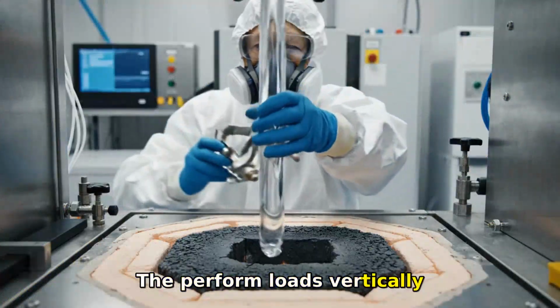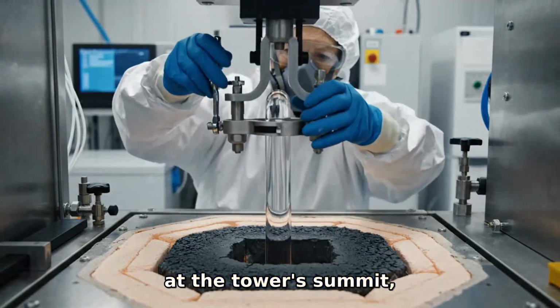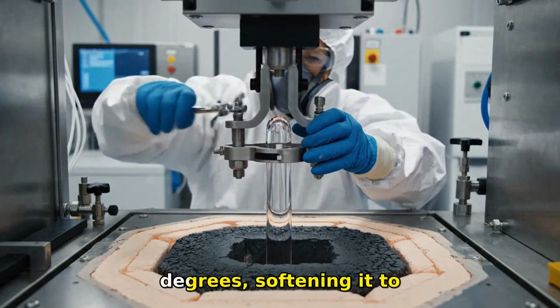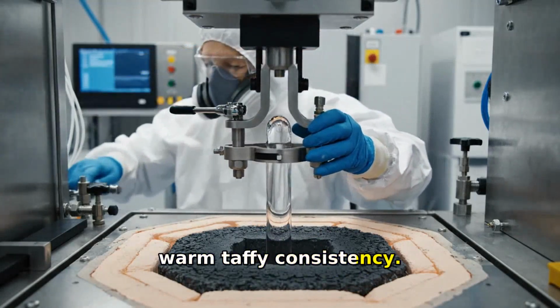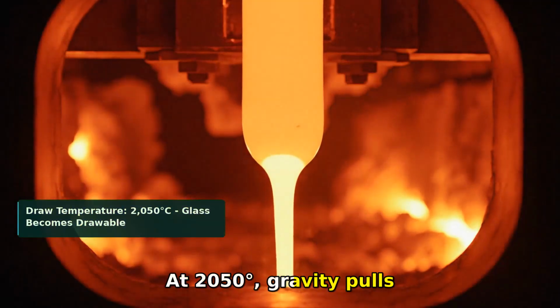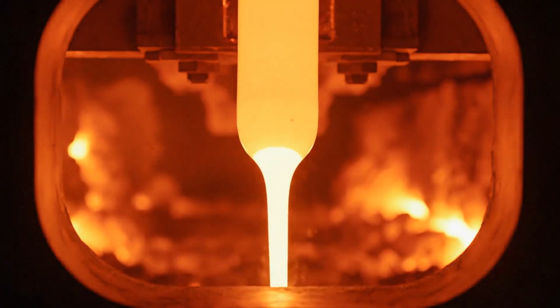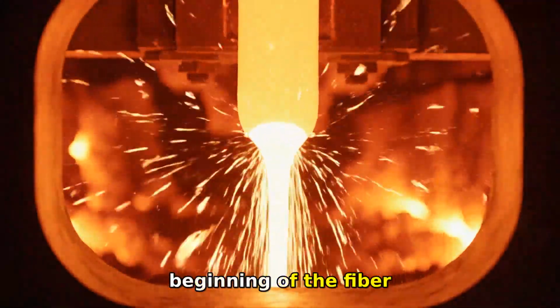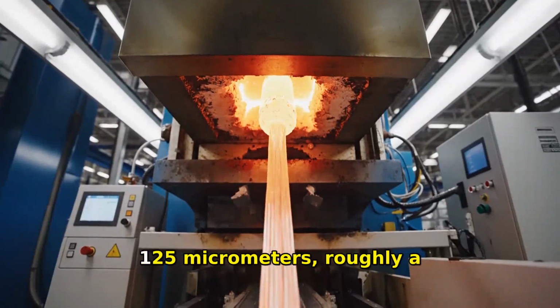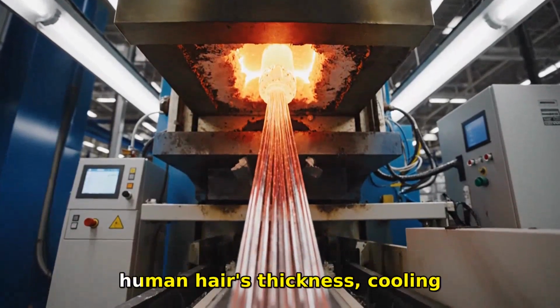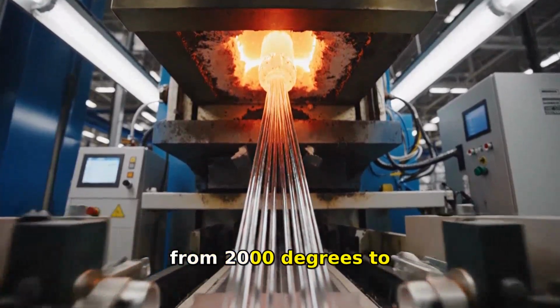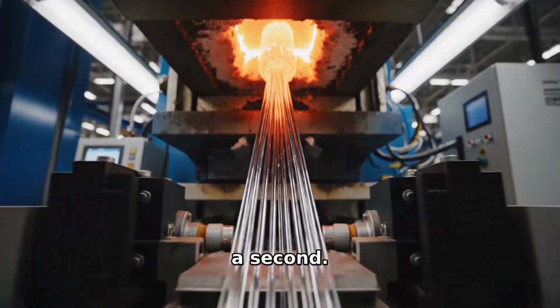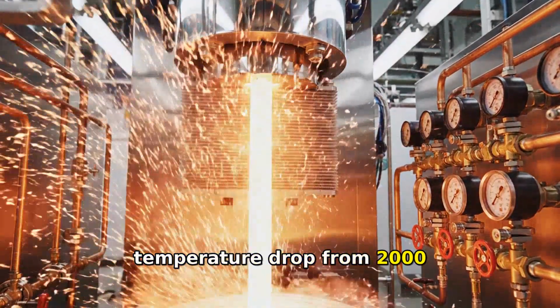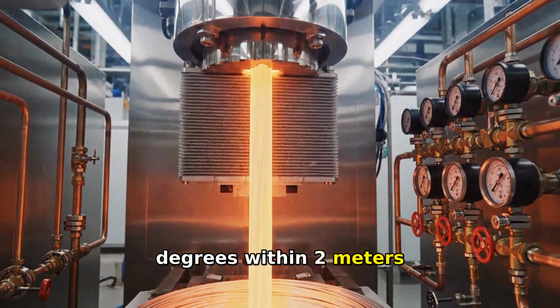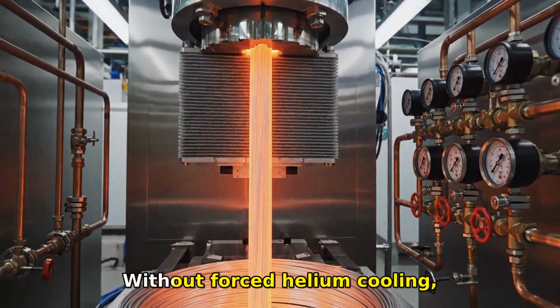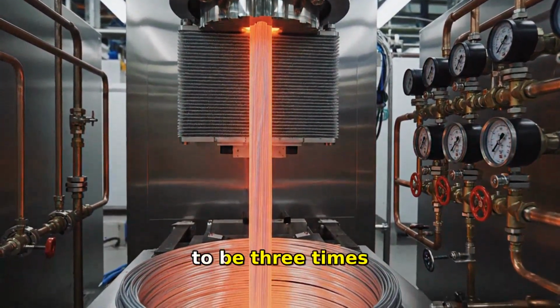The preform loads vertically into a graphite furnace at the tower's summit, heating the glass tip to over 2,000 degrees, softening it to warm taffy consistency. At 2,050 degrees, gravity pulls the molten tip downward, forming a thin neck that stretches into the beginning of the fiber strand. The fiber emerges at 125 micrometers, roughly a human hair's thickness, cooling from 2,000 degrees to room temperature in under a second. Helium cooling accelerates the temperature drop from 2,000 degrees to below 50 degrees within 2 meters of vertical travel. Without forced helium cooling, the tower would need to be 3 times taller.